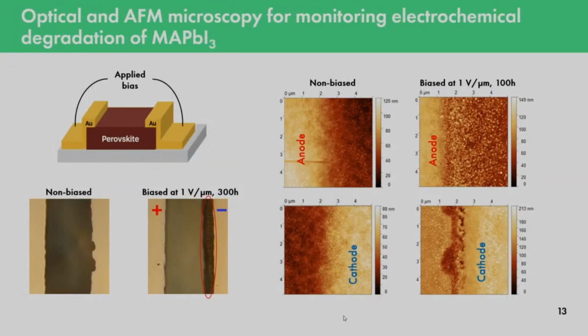To understand what's going on in the material itself, we decided to make this lateral configuration of device. We applied electrical bias to gold contacts. One thing that should be noted is that all experiments regarding biasing of devices were performed in an inert atmosphere, without oxygen, without moisture, and in the dark, to avoid any combination of various factors and to observe only the influence of the electric field. After biasing the lateral device, we observed some changes in the perovskite film. For example, along the cathode, the formation of a kind of canyon can be observed on the optical photograph visible here, and on atomic force microscopy it's visible like here.